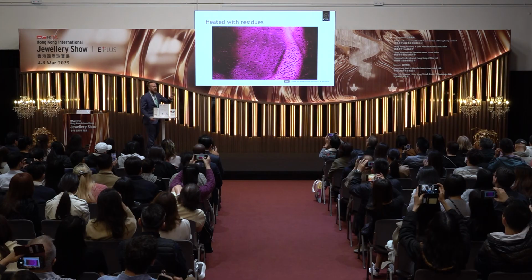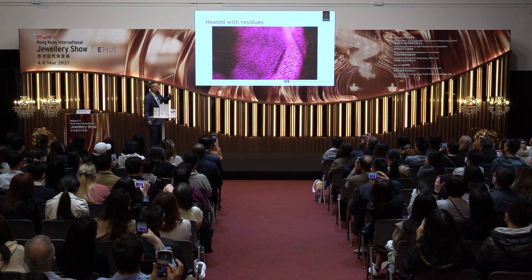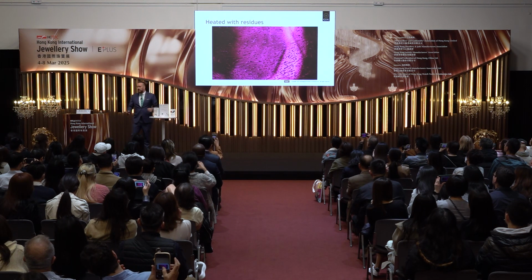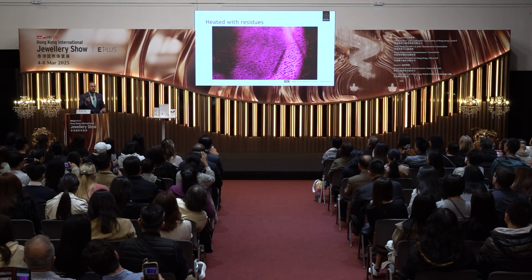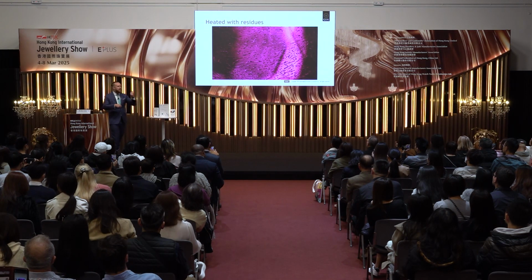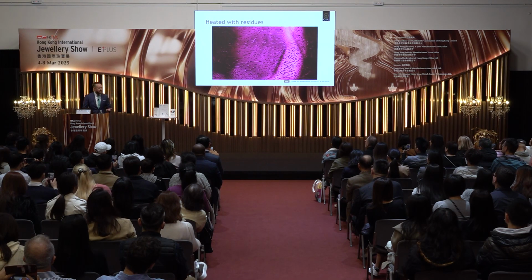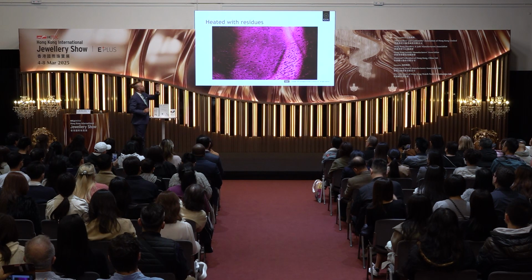And this is what is left. So this used to be a completely open fracture. This used to be filled with air. But now you can see that there is only these droplets of flux that remain, that is the scar, but most of it is actually filled with corundum now. So it has the same hardness, it has the same durability, it has the same chemical resistance as the rest of the corundum. That is completely healed, and we are only left with that scar where that fracture used to be.